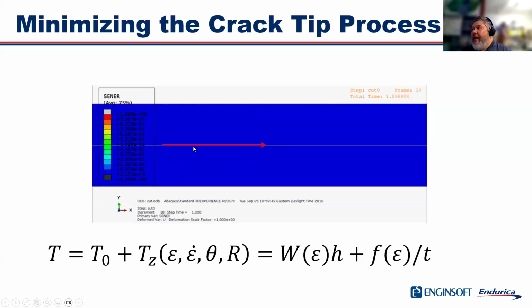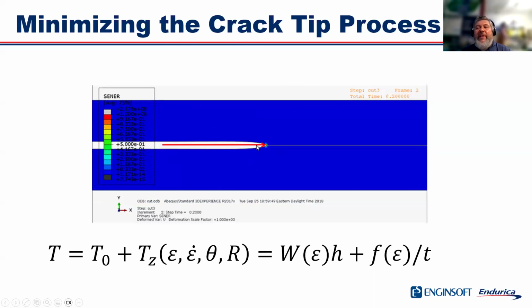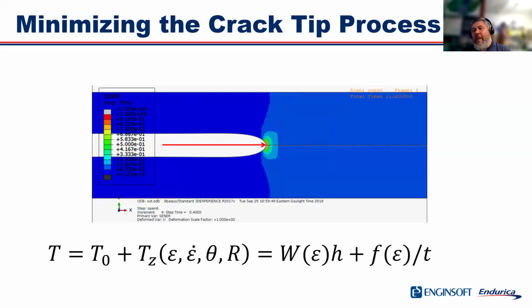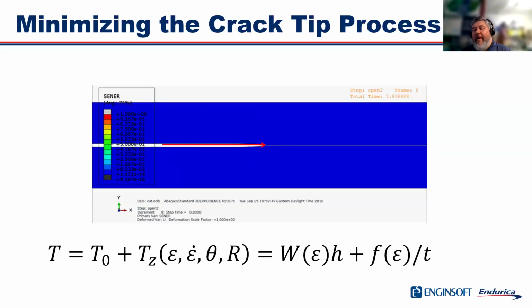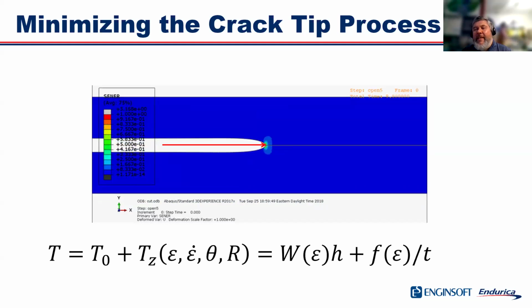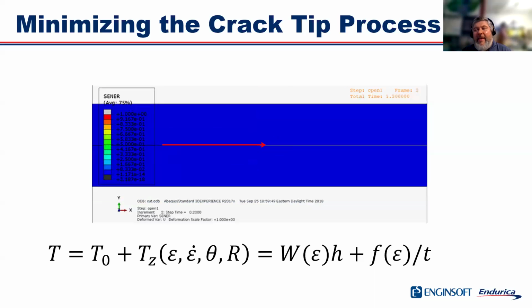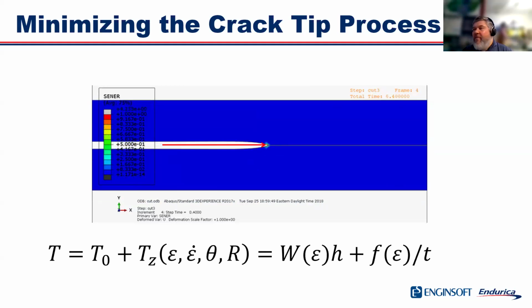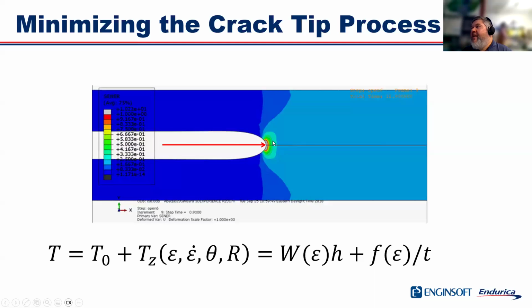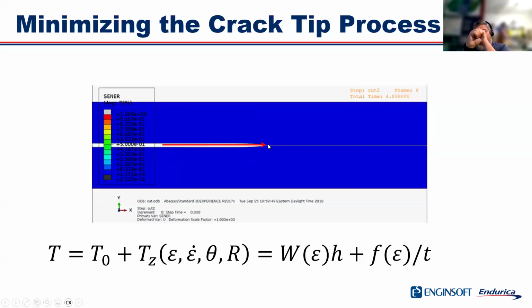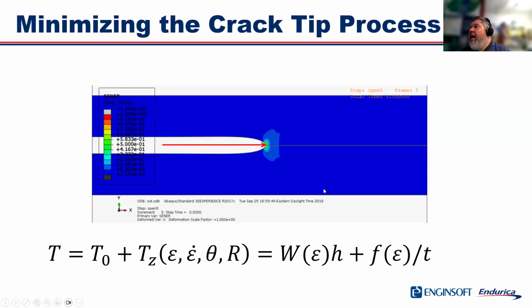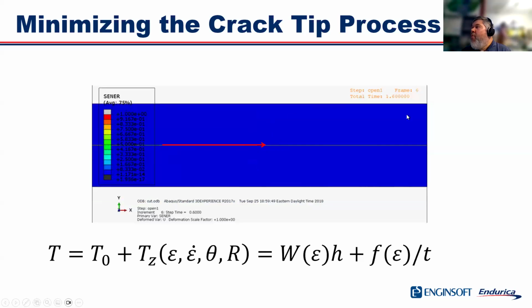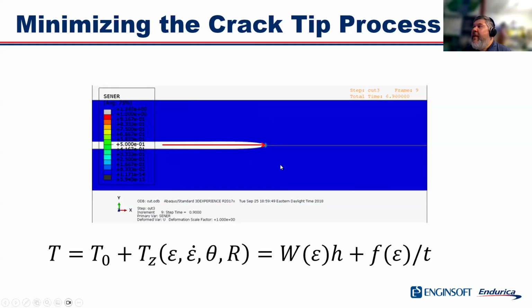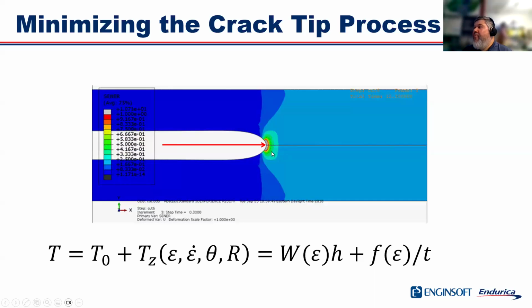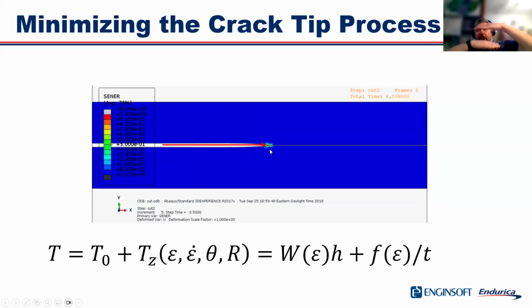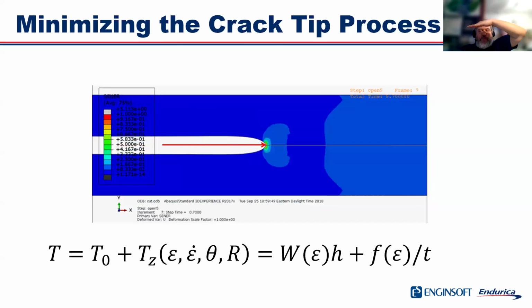The reason that cutting with a blade works to do this is that the order of the crack tip singularity when you have a blade is a higher order than if you don't have a blade, which means that the crack tip process zone is greatly reduced when you have a blade. And what you're looking at here is a finite element simulation that shows the size of the process zone as a function of the amount of stretch that you put on the rubber.